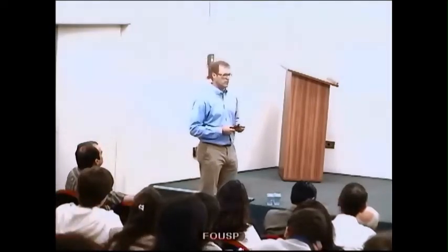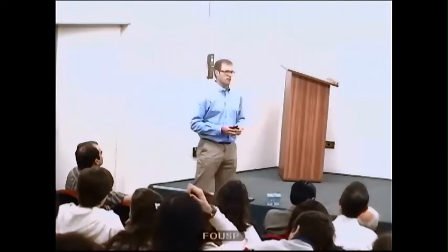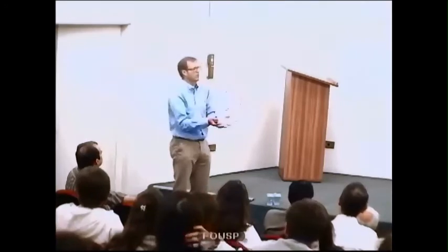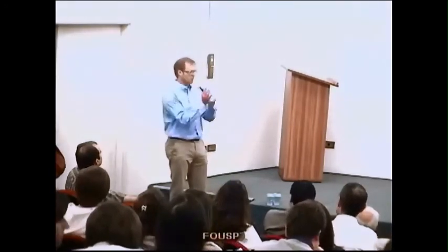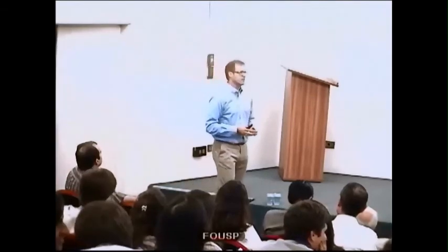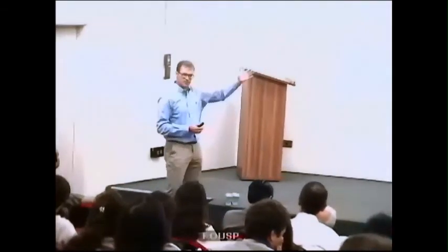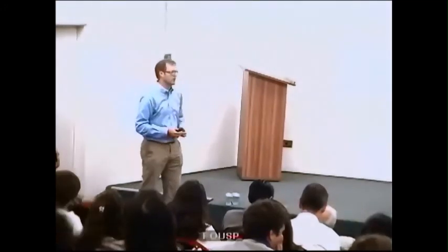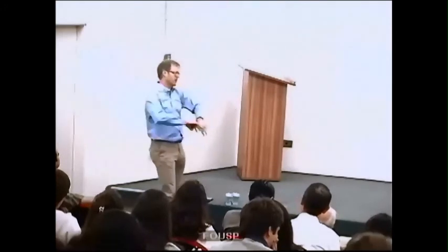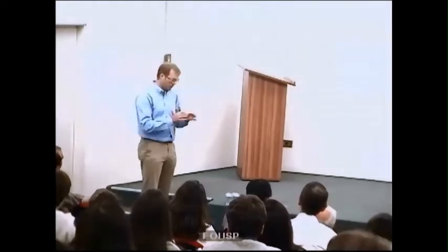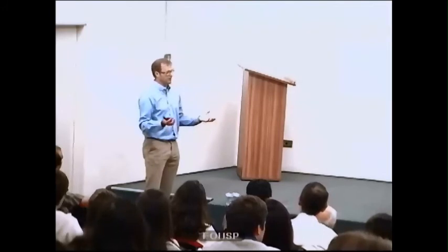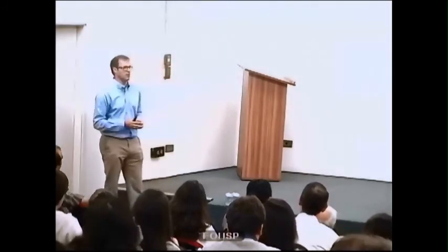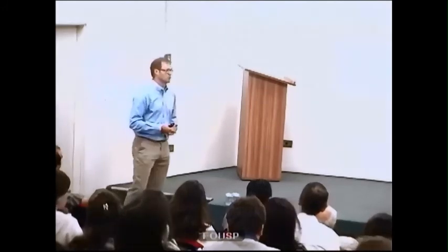Well, once there are too many pores, of course, it's a problem. But a pore itself has a perfectly round-shaped appearance. There are no sharp edges like that. It's not that dramatic as it seems from a fractographic image once you have a lot of pores. And even this pore was far away from the tensile zone, so I don't think it's influencing. If we do a test, let's say strength or fatigue, we afterwards look at the fracture surfaces, and we see, for example, materials with a high strength, and there are so many pores inside. And there, we have the feeling there is not a real correlation, as long as there are not too many pores inside, of course.